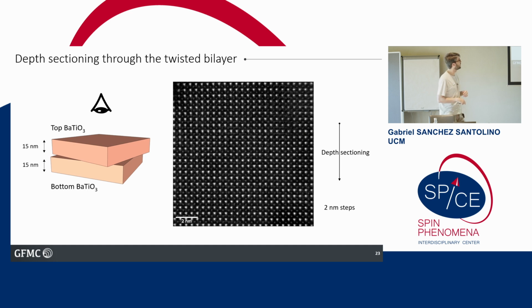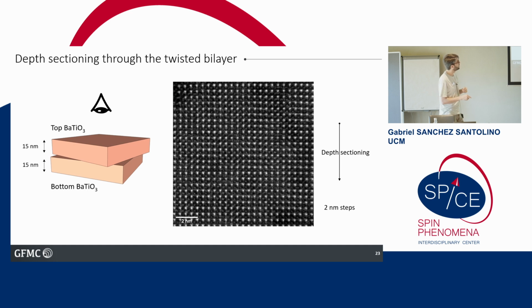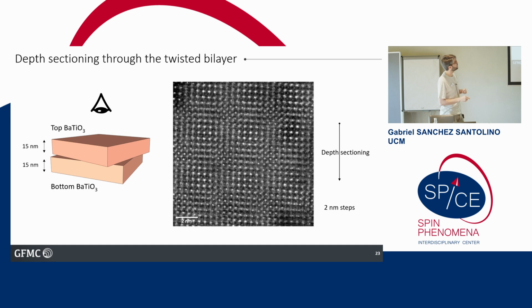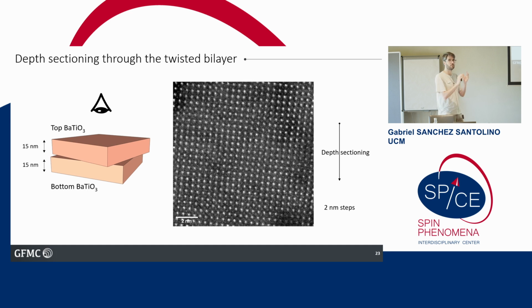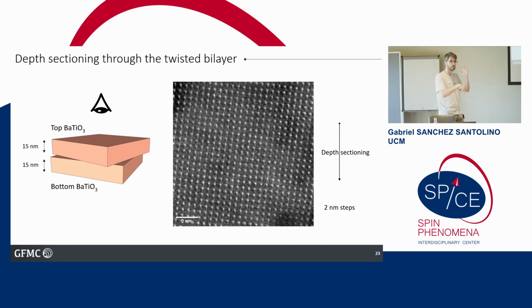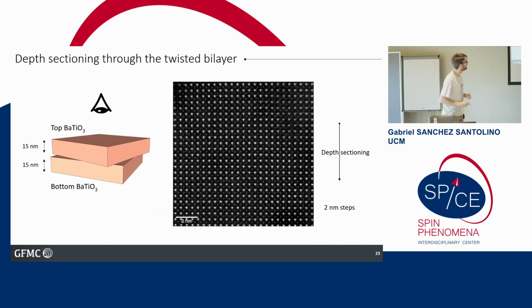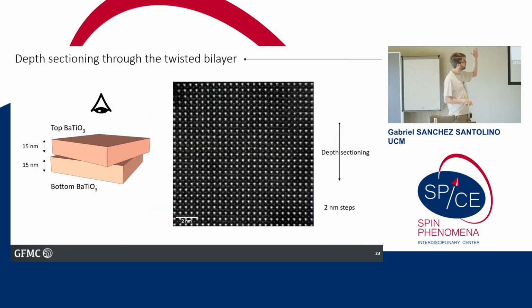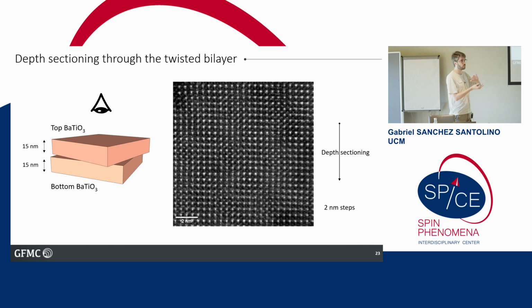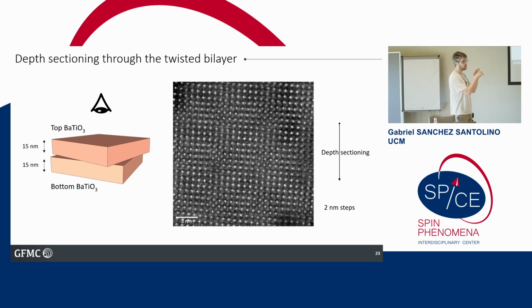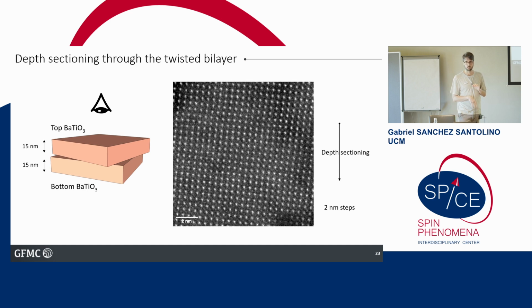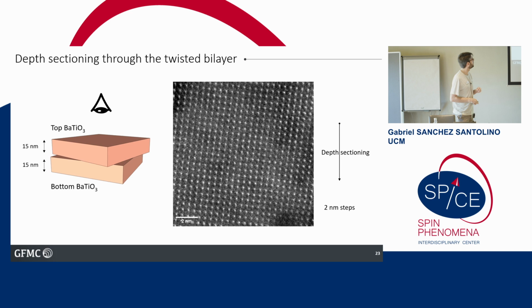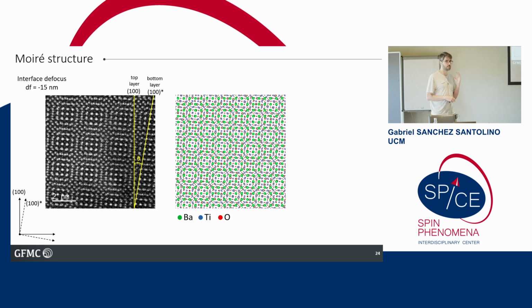You are going to see how we can see the top layer, and then we start seeing the bottom layer, and when both layers are in focus at the same time, we have the Moiré contrast. Then we go to the bottom layer, and we can study both layers independently, which is very, very important for this. I'm going to play this again, maybe, yes. So we are focusing on the top. We go through the middle of the sample to the interface. We see the Moiré contrast, and then we exit the sample at the bottom, right? So we have a look at the Moiré contrast in the middle.